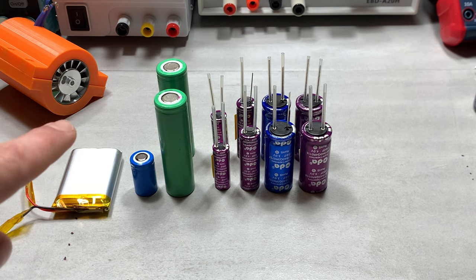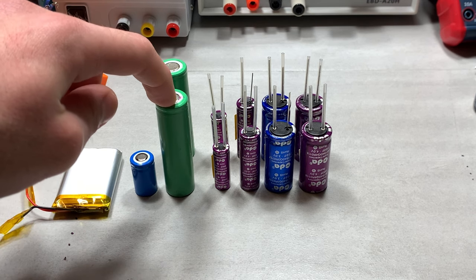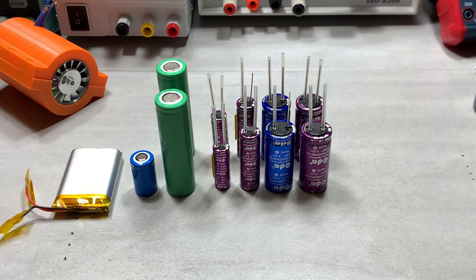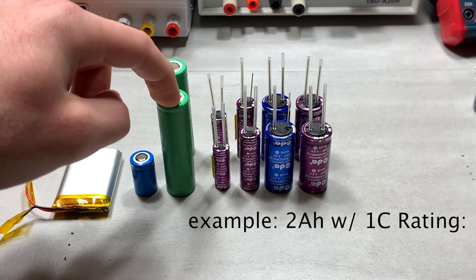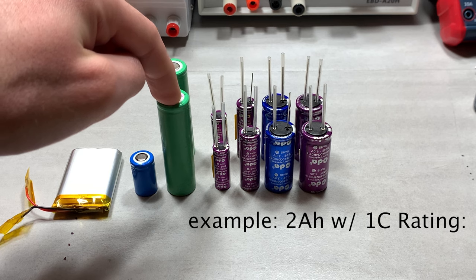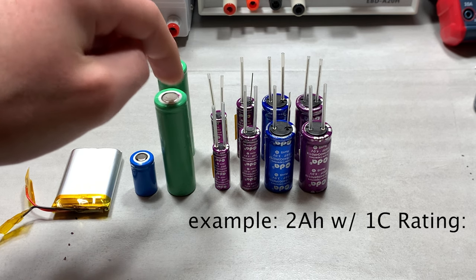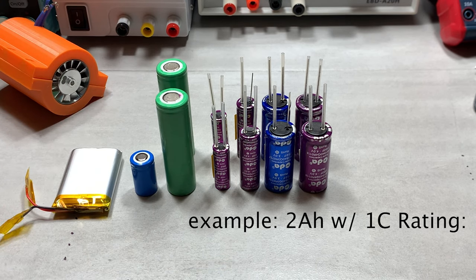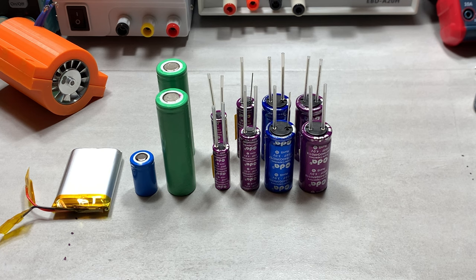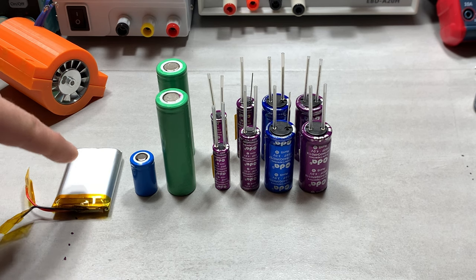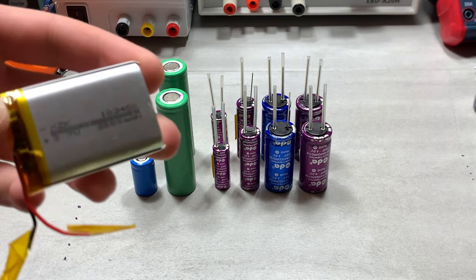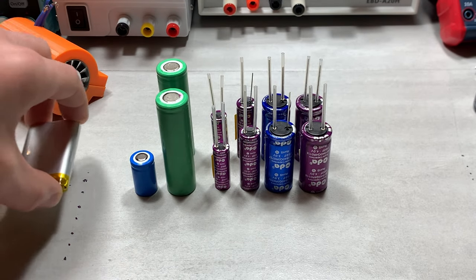And basically all that means is that let's say you have a 2.2 amp hour battery. So for simplicity, let's just say it's 2 amp hours. If you have a 2 amp hour battery, and it has a C rating of 1C, that means you should not discharge the battery at more than 2 amps of current, charge or discharge. It's that simple. So with this one, this lithium polymer is 2.4, 2.5 amp hours, 2 amp hours only.